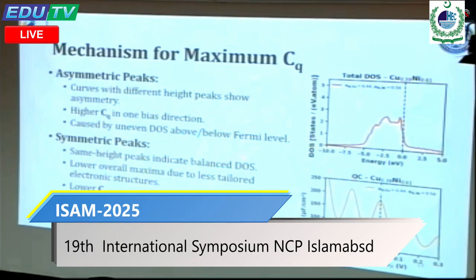After analyzing all of the 100 curves, we can say that the composition which includes copper 39% and nickel 61% is the best suited for the supercapacitor electrode.